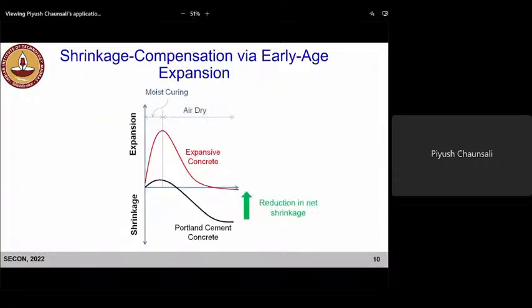So we can also look at the dimensional changes. What you see in this case, during this hydration of yeelimite, there is an expansion. So we saw that earlier, the expansion. So you see there is a change in the dimension. So this much expansion is there in expansive concrete. But this concrete also later on dries. So what you see, the black curve is typically what you see for Portland cement concrete. So we say that this much shrinkage is there, right?